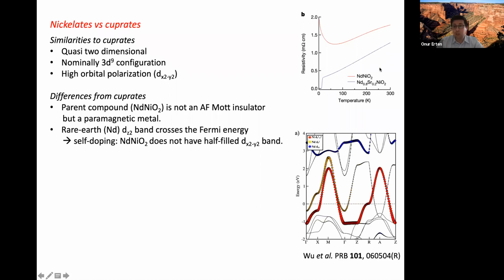When you look at the band structure, here the red band is the dx²-y² orbital. These are density functional theory calculations. And in cuprates, you only see this band, okay? So in cuprates, only this band crosses the Fermi energy. And that's why if you are in d9, it would be half filled. But in nickelates, there is an extra band that comes from the rare earth atom, neodymium, that has mostly z² characteristics. And that crosses the Fermi energy too, and it is partially filled.